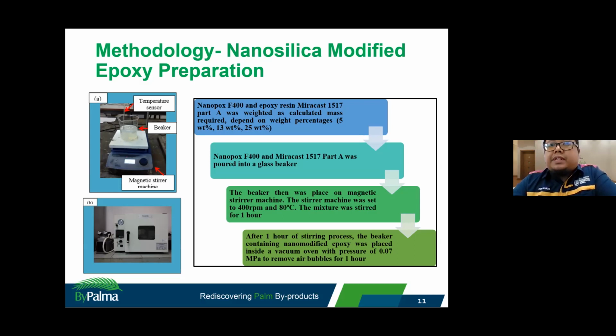After 1 hour of stirring, the beaker containing nano-modified epoxy was placed inside a vacuum at a pressure of around 0.07 megapascal to remove the air bubbles for a duration of 1 hour. Okay, this is an important step for the stirring process because the problem with nanosilica is that it easily agglomerates inside the epoxy. That's why we use this step. It has been proven by my supervisor, Associate Professor Dr.